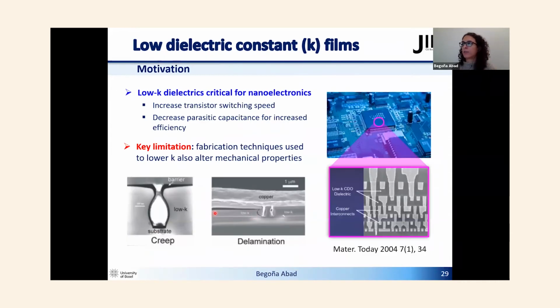Okay, so now I change a little bit to the ultra-thin films. In this case, the motivation to study these low dielectric constant films is that these low dielectric constant dielectrics are critical for nanoelectronics. So we really want a very low dielectric constant to increase the transistor switching speed, and also to decrease the parasitic capacitance that happens between the metallic connections. However, when we reduce this dielectric constant, what happens is that mechanical properties get degraded.